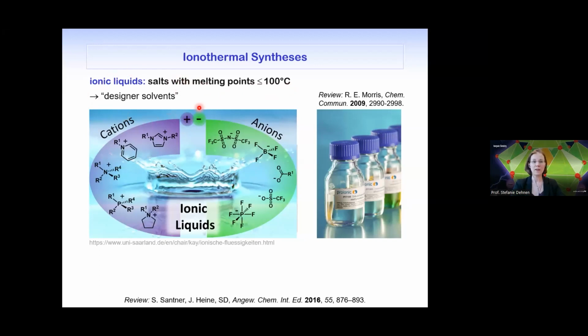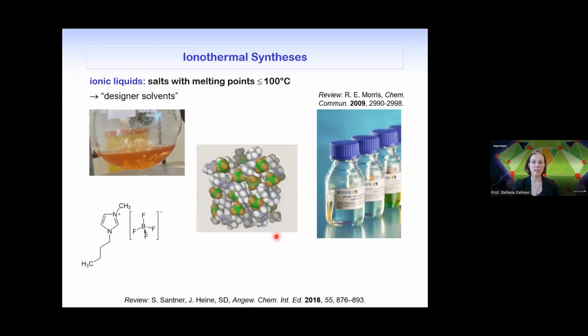And this gives them a character as a so-called designer solvent. Because you can use different kinds of cations, different kinds of anions to form this ionic liquid, the only precondition is that the salt structure must be very bad. So it doesn't want to crystallize, and this is why it's melting at such low temperatures. And here you can see just a movie from my lab. So these ionic liquids are viscous liquids, and you can do chemistry in them like in solvents, and they can have different colors and different viscosities and so on. And one type of ionic liquids is imidazolium based, and this is what we are using all the time with a variety of different counter ions.